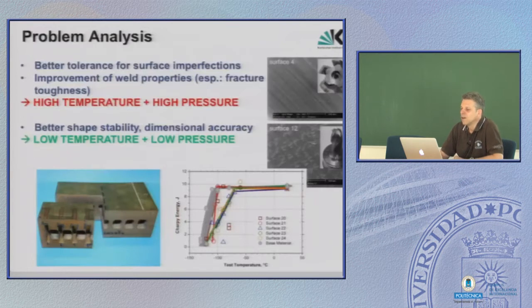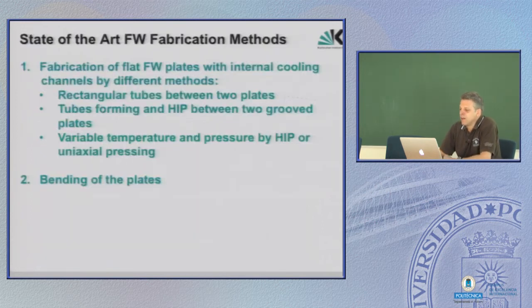So we had good parameters to produce this. Everything is okay. High temperature, high pressure leads to perfect welds, but unfortunately it leads to a completely useless component. So we have to think about better ideas again. Better stability would require low temperatures and low pressure. Then we had a good component theoretically, but then the blades didn't glue together, they would come apart, so also a useless component in the end.